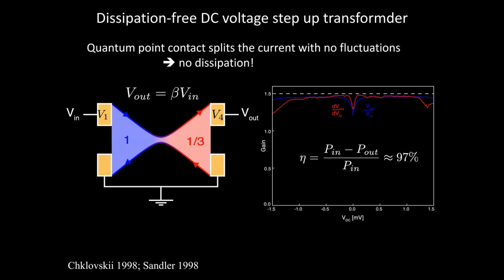But here this perfect current mirror is not powered by some transistors. It just comes from the fact that you've made a single adiabatic junction between two fractional quantum Hall edge modes. So just to give you the idea, what's happening is you're driving a voltage in. It drives some current. There's some current mirroring that happens at this junction, and then there will be some voltage that develops on this output electrode. And if you work it out, you find that it's higher, 3/2 higher. Now, if this is a perfect current mirror, then there are no fluctuations. Every time you put in a 2e, you get a minus e coming out the other side. If there are no fluctuations, there's no dissipation.